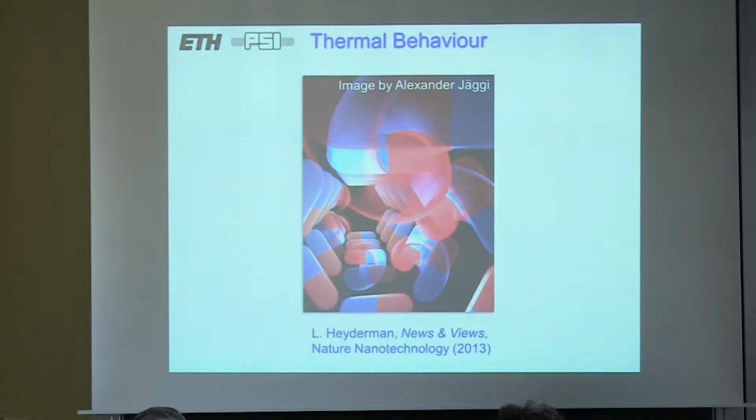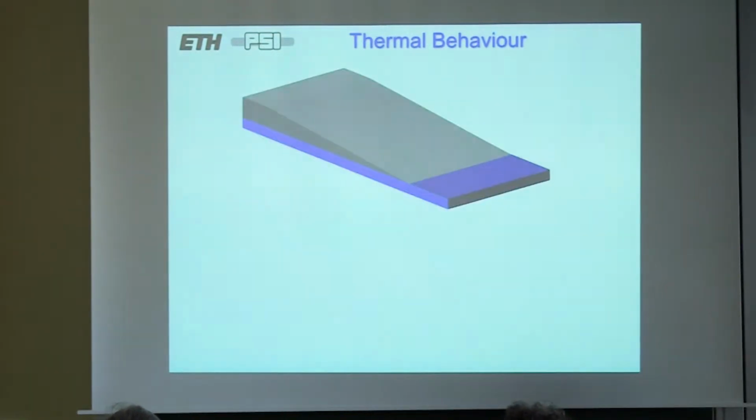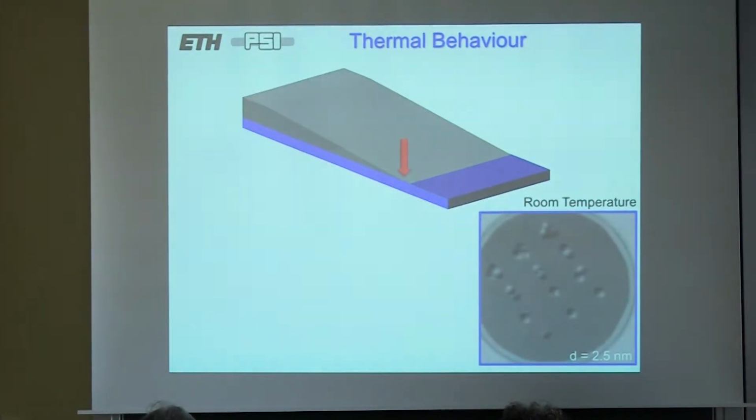Now, in recent years, people have been interested in systems with superparamagnetic islands. That means that the moments are free to fluctuate backwards and forwards, so each nanomagnet has two states. In order to look at these, we came up with the idea of looking at a wedge sample, so that you can easily find the sweet spot in your microscope where these moments are fluctuating at the time scale of the imaging technique. At the low thickness end of the wedge, the moments are fluctuating in a collective manner. And if you focus on this structure here, the structure is fluctuating between these low energy configurations.